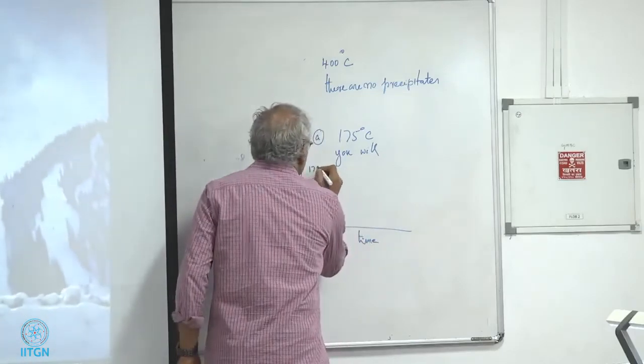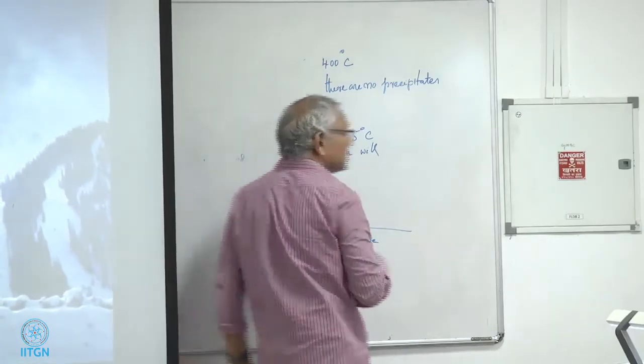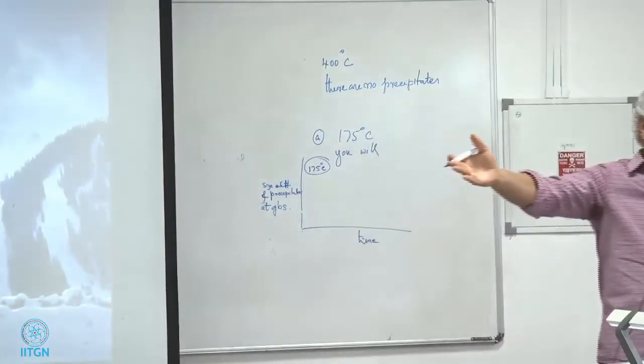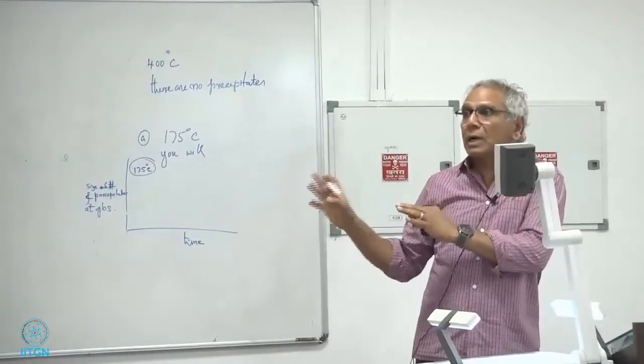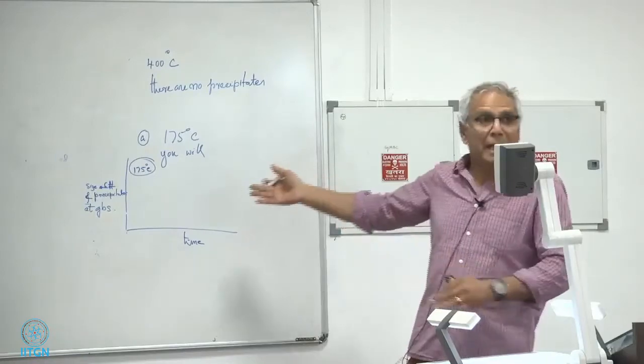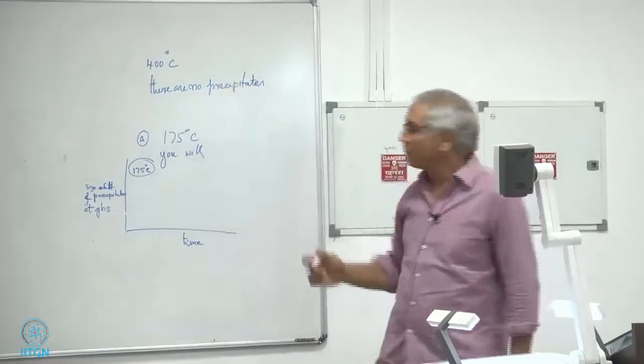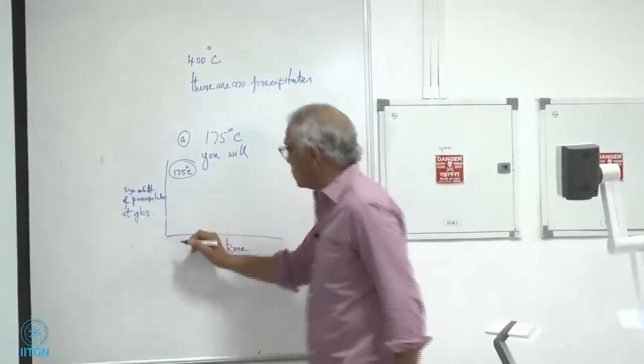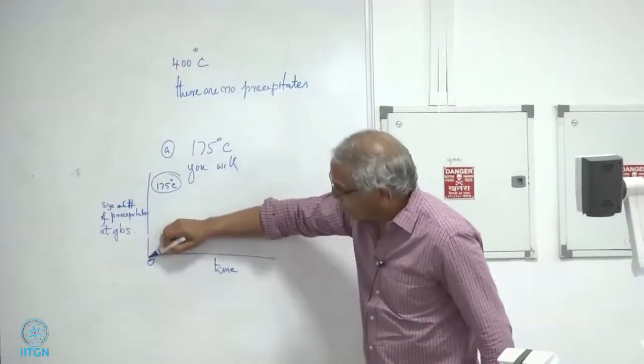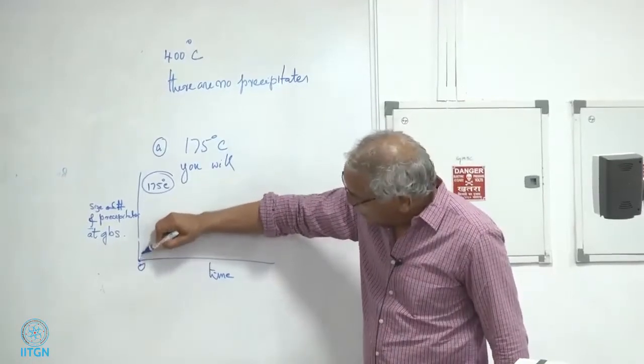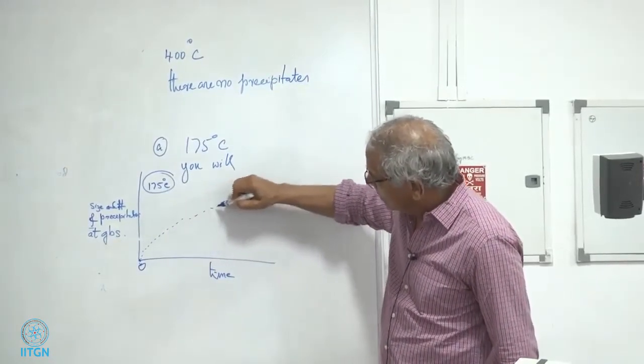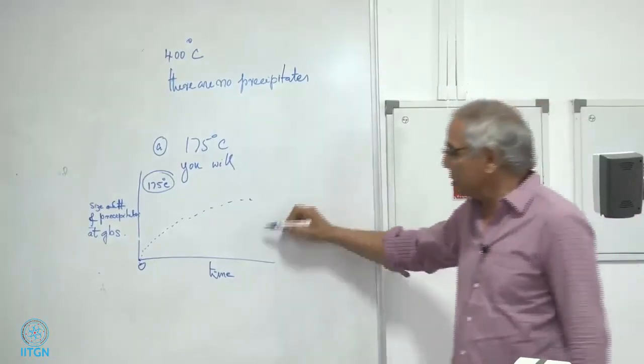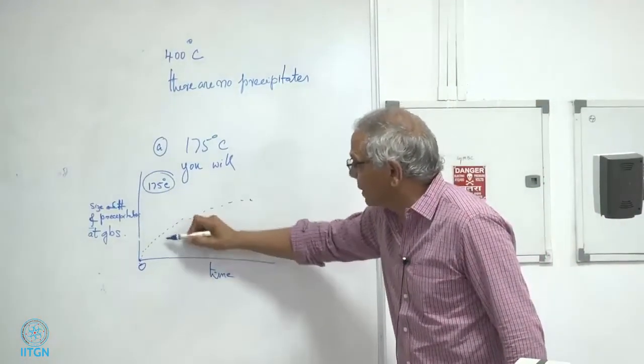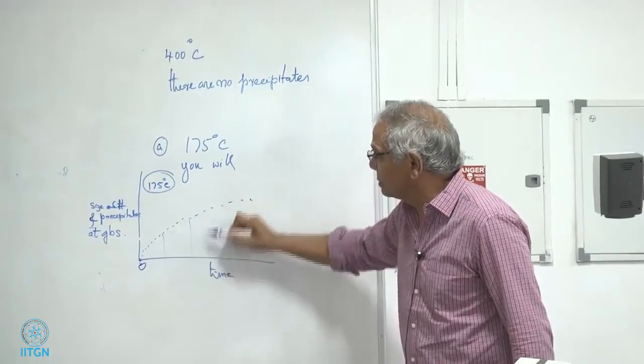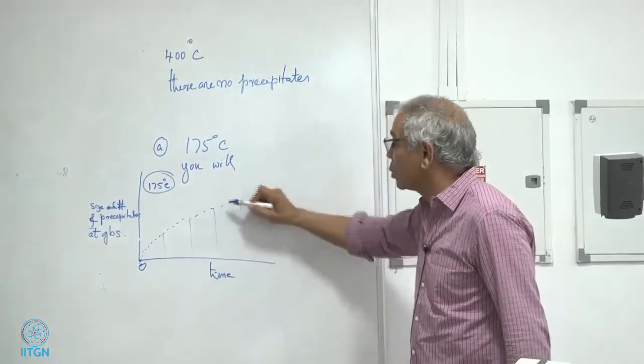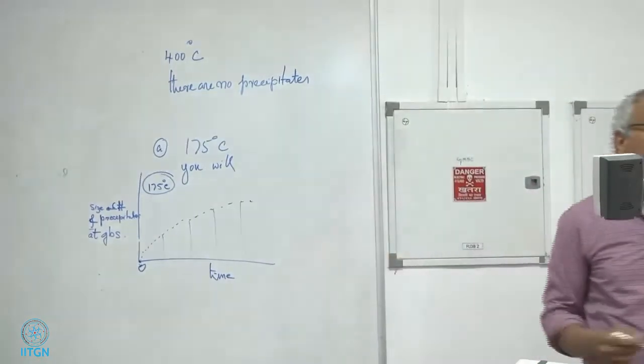And I'm heat treating this at 175 degrees Celsius. Like Sir said, this is not actually an age hardenable alloy, it's a work hardening alloy. But this can happen. That's what we saw. So at time 0, there are no precipitates. Then slowly the precipitates form. I'm doing it at 175, maybe 10 hours. I don't know which way the curve will go. That's what will happen.